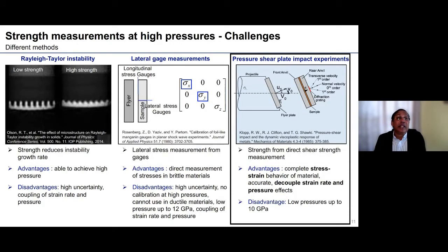So we are not the first ones to think about how to measure strength at high pressures, but there are many challenges associated with it. One very interesting technique, used both in plate impact or impact related experiments as well as laser shock experiments, uses the Rayleigh-Taylor or Richtmyer-Meshkov instabilities, whereby you put small perturbations on the surface of the material, and this is being shocked.